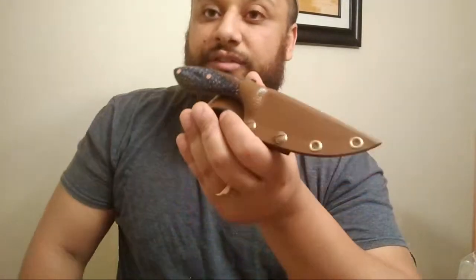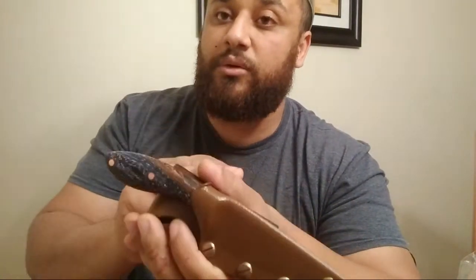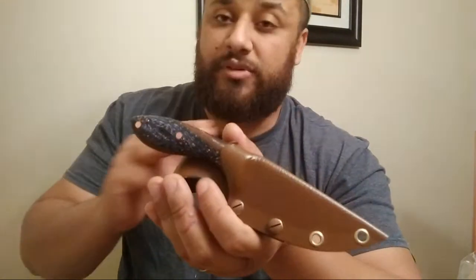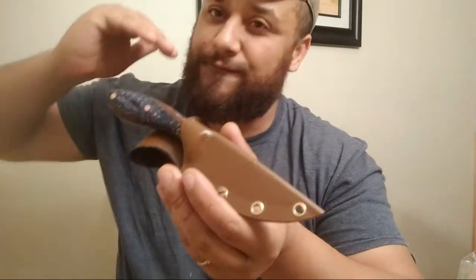Vancron Super Clean is the 2019 upgrade to Vancron 40. What they did was drop the molybdenum and the tungsten. For some people, that's like, why would they drop that? You don't want that in this kind of steel because it competes for carbides inside this metal. You only want vanadium nitrides in this steel. You don't want softer M6C. When I say M, it can mean both wolfram or tungsten or also molybdenum. So Mo6C and W6C are soft carbides. They're not the hard tungsten W2C and WC carbides, because in the presence of chromium, which makes this an air hardening steel and makes it very annealable, you don't want that in it. You just want the finest, hardest carbides possible.